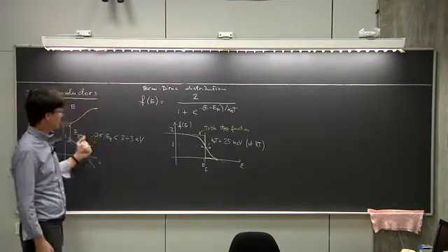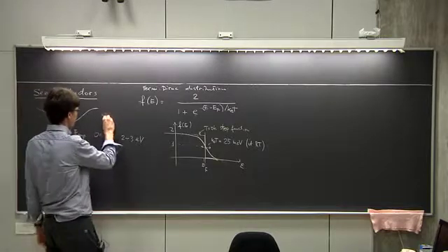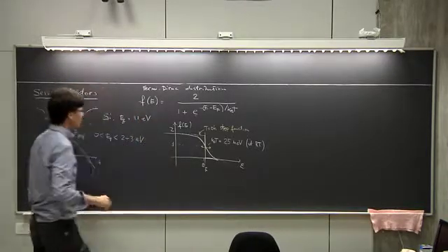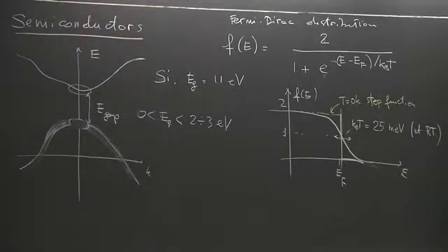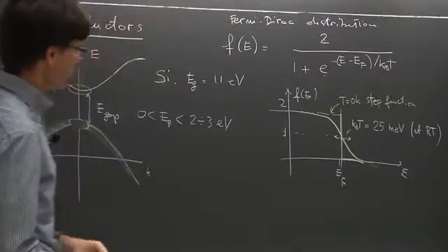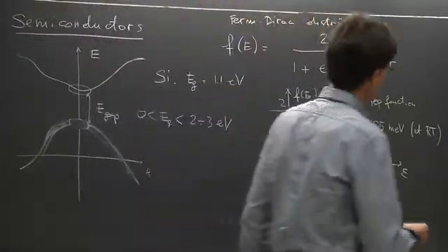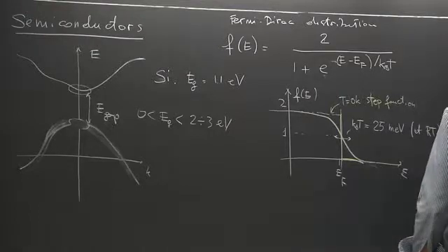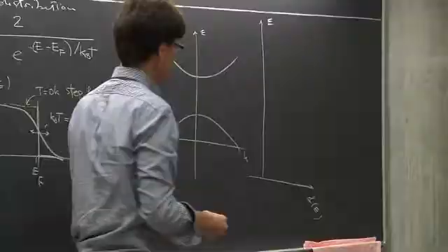The typical case is that the semiconductor has an energy gap of, take silicon, for example. Silicon has an energy gap of roughly 1 electron volt. So just to give you an example, if you take silicon, the energy gap is equal to 1.1 electron volts. So clearly, 25 millielectron volts with respect to 1 electron volt is much smaller. What this means is that this energy gap is much larger than the width of the distribution. And therefore, let me now repeat the plot here, and now here I plot f of E as a function of E, right?